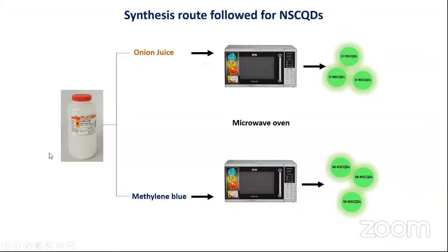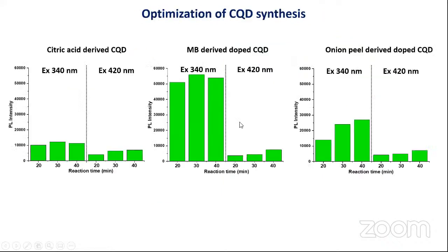We are using citric acid, which is a very good catalyst, and it also produces good carbon dots. Here we take the precursor and methylene blue and put them directly into the oven, and then finally we get the carbon dots. Here we have optimized the synthesis. We varied the reaction time from 20 to 40 minutes, and we also checked the excitation from 340 to 420 nm, in the visible and UV range.